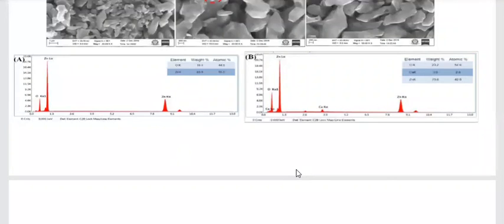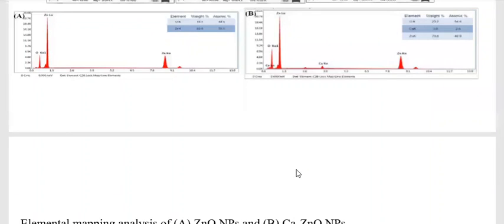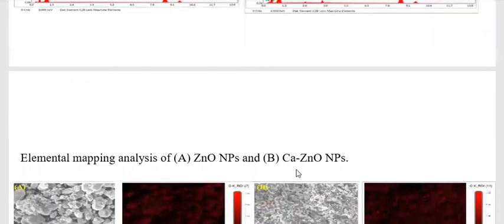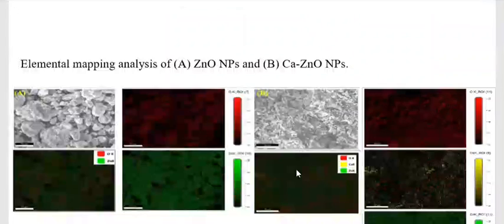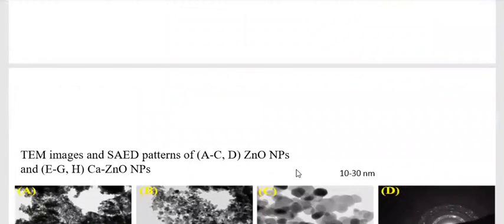The TEM analysis also shows the spherical morphology, a minute spherical structure of 10 to 30 nanometers. By contrast, the calcium doped nanoparticles showed 100 to 400 nanometers. When doping the calcium ion, the particle size increases, with spherical morphology.